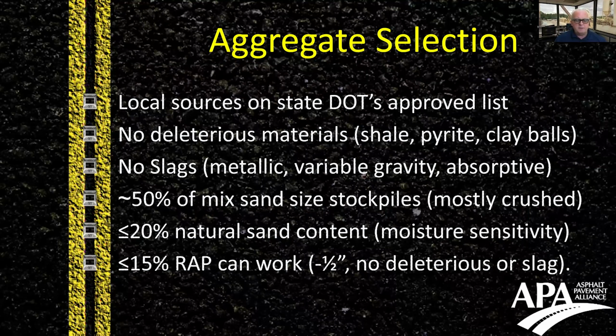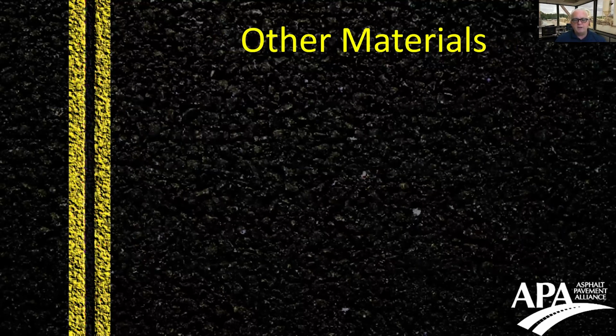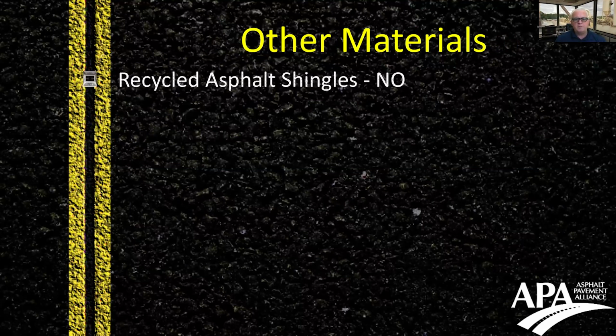And you can make up to 15% RAP work as long as it's processed minus a half and it fits the gradation of the mix that is being produced, as long as the RAP does not have any deleterious materials or slag. So essentially, if you've got a RAP that has the same material limits as the virgin stockpiles, then you can typically use up to 15% in this mix. But I would be very cautious about that, depending on how much experience you have with the mix and with the material.